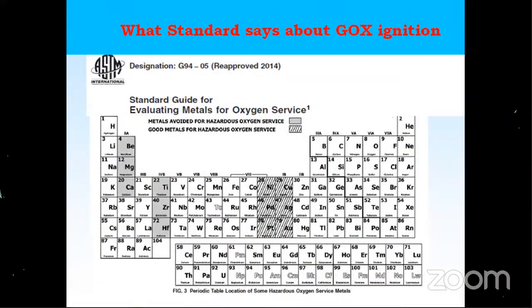This is the ASTM standard, which says which are the best and the worst materials for oxygen application. We cannot use magnesium, beryllium, calcium, titanium, zirconium, hafnium, and aluminum also is part of that, because aluminum generates a lot of heat of oxide. The best materials are nickel, copper, palladium, silver, platinum, and gold. In fact, palladium, silver, platinum, and gold we cannot use, we can give a coating at most. They are not engineering materials. So most materials for oxygen applications are based on nickel and copper.